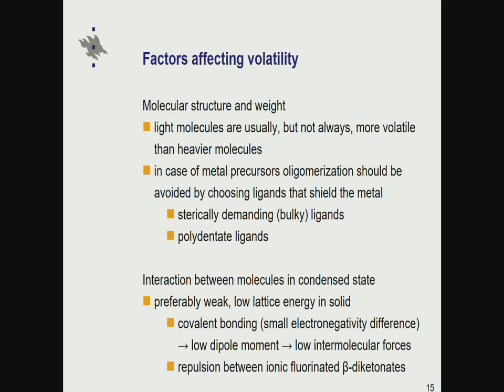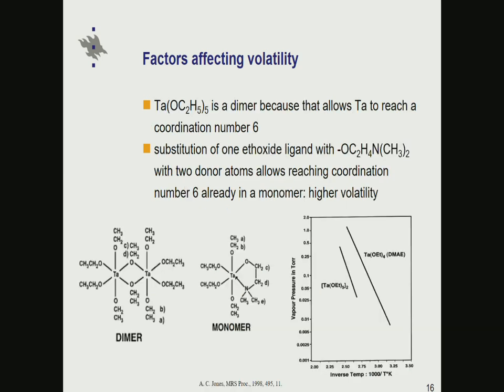There is also one quite common way with metal precursors, which has been to play with fluorinated ligands. One adds fluorine into the ligands, and as a result creates a sort of ionic type of interaction from fluorine to fluorine from one molecule to the other, decreasing the interaction. But really the molecular structure and weight is very important for the MLD precursors, for these organic molecules. What we have so far studied, in choosing precursors for MLD, has taught us that quite rapidly we actually reach such molecular sizes that the volatility really becomes a limiting factor in using these precursor molecules. And that's obviously something we need to deal with in HYCOAT quite a lot in the future as well.